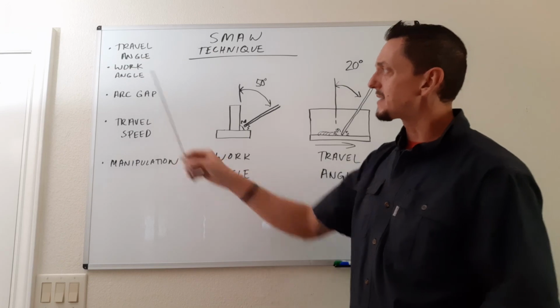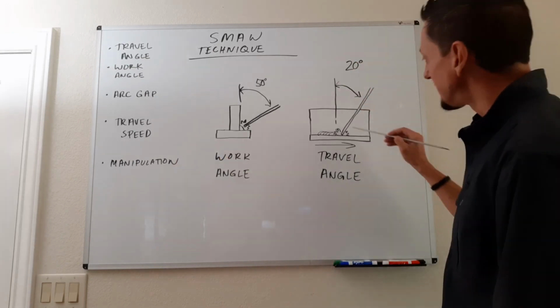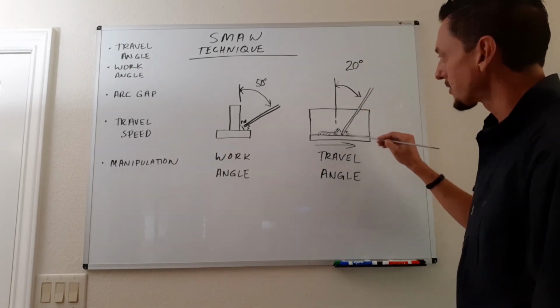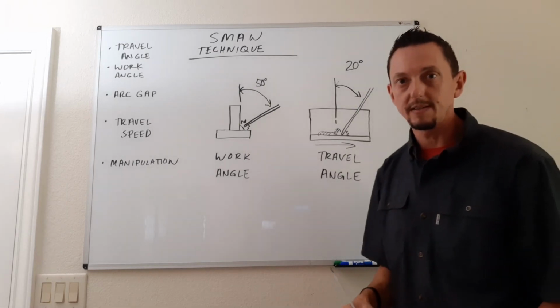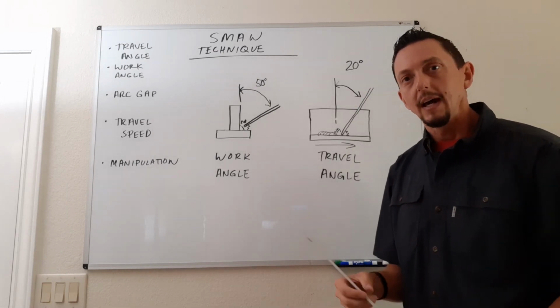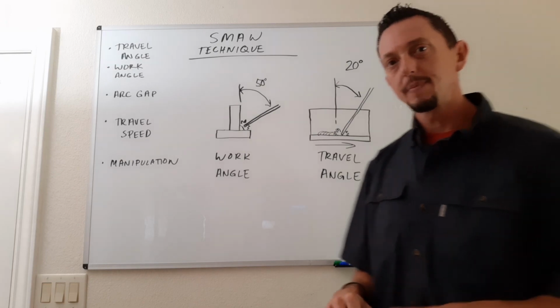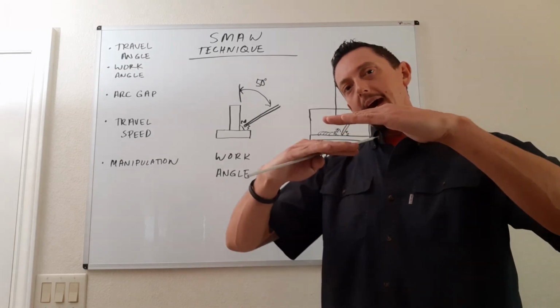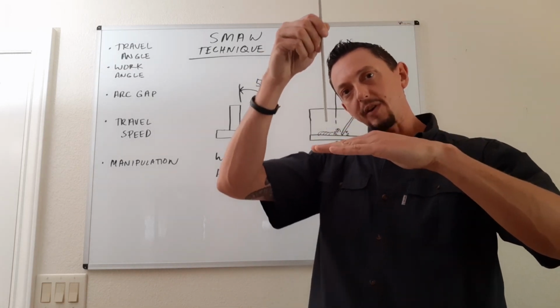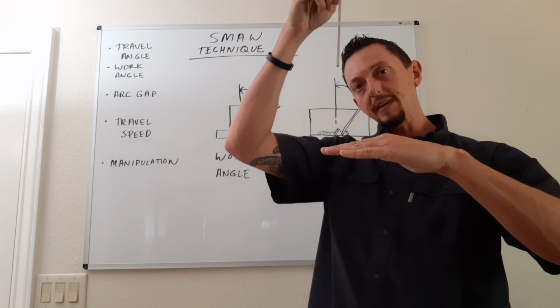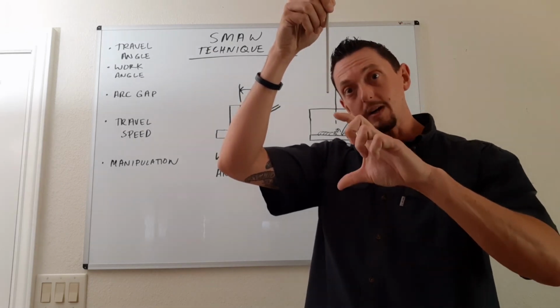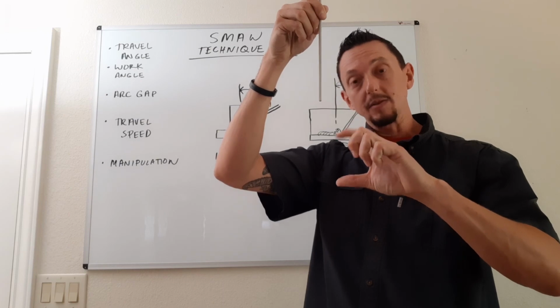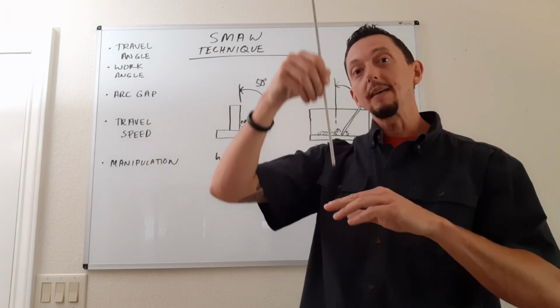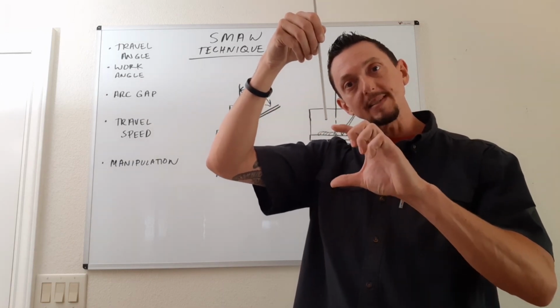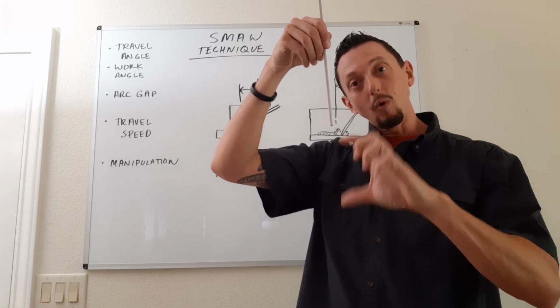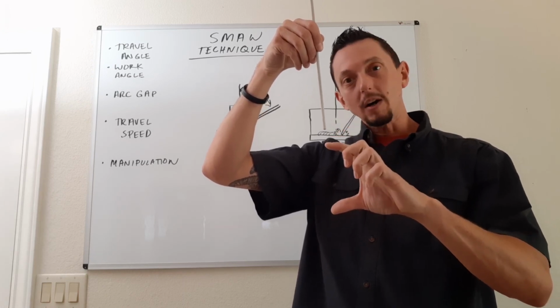Now the other thing is our arc gap. So that would be the distance between the end of our electrode and the work surface, okay, or our arc. And that is very, very important, especially with stick welding, because as the end of our electrode gets further away from our work surface, the arc gets hotter and more erratic. Okay, so I'm going to repeat that. As we get further away, we get more resistance in our arc, and that creates more heat, but it also makes the arc more erratic.